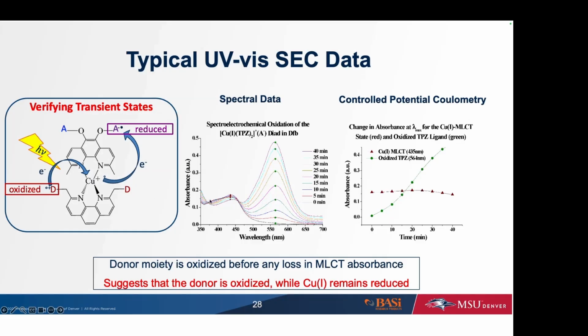And what we were trying to do in this situation is we were looking at this donor chromophore acceptor where we had light come in and excite a copper 1 center, which created an excitation to a metal to ligand charge transfer state, which then triggered an electron transfer out to an acceptor. But the tricky part of this complex is that it is difficult to re-reduce the copper and then oxidize the donor, because it's hard to find an oxidizable donor that has a redox potential that is competitive with the 2-1 couple on the copper.